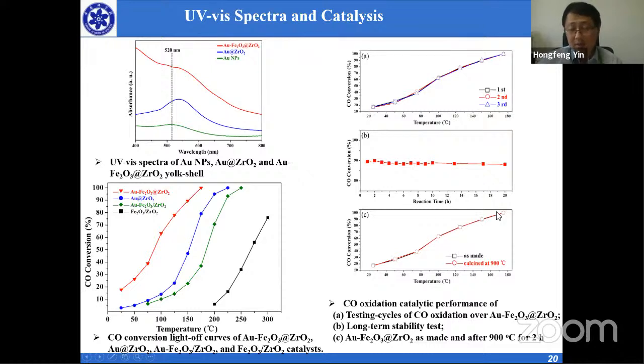And then here is a pretty good result. As I mentioned, nanoparticles are easy to aggregate, especially nanocatalysts. But for this structure, we calcined at 900 degrees Celsius and did the catalysis. Again, we can see that the light-off curve matched pretty well with the original one. That means the structure did not change. So it has very, very good, outstanding thermal stability.